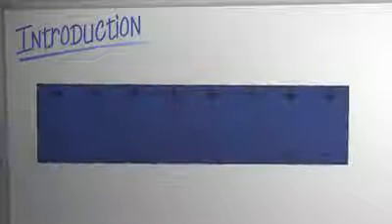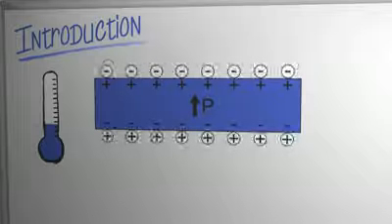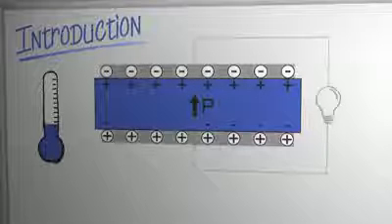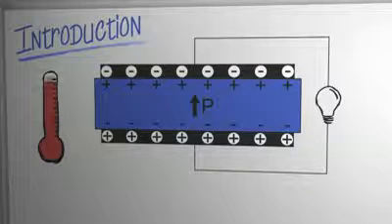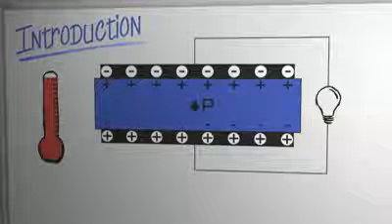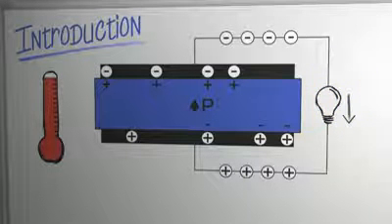Pyroelectric materials are a subgroup of dielectric matter marked by the presence of a non-zero electric polarization in absence of an electric field, the so-called spontaneous polarization. At a constant temperature, surrounding charges compensate the arising charges of opposite sign on the crystal surfaces. Connecting an external electric circuit and heating the sample will cause a change of the spontaneous polarization, which is accompanied by a redistribution of the surface charges. Compensating charges enable an electrical current flow in the circuit.